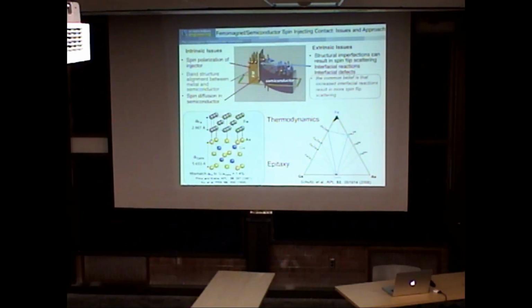So years ago we started all of this, and we said, well, iron is a very good ferromagnet. Iron, if you look at it, if I put 4 unit cells of iron on top of gallium arsenide, the mismatch is 1.4%. So it looks very good for epitaxy. It's not a big mismatch.